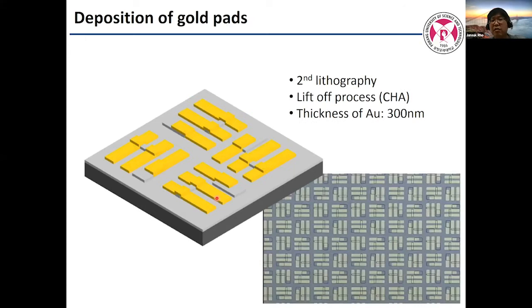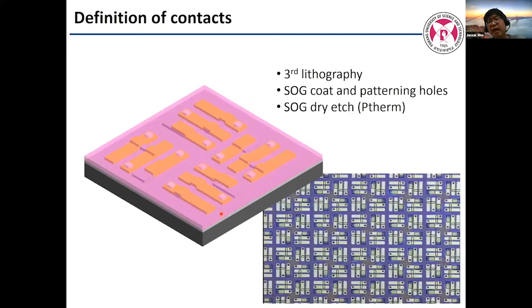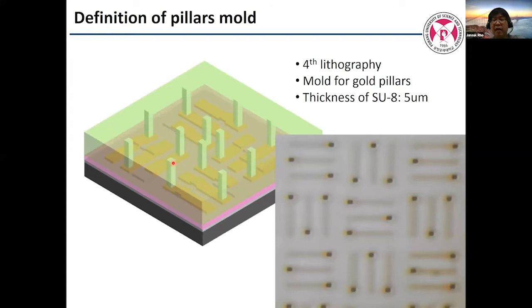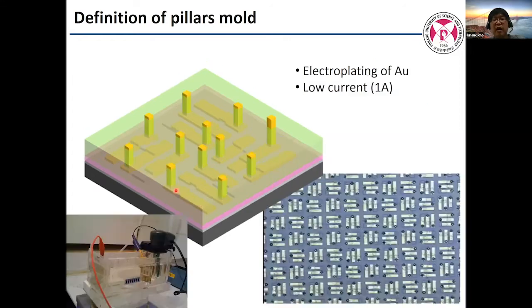And then this is the second lithography. You can see the alignment, as usual, the micro mask aligner can do alignment very well. This is a gold pad lithography, and then gold deposition and lift off. Third, we coat with spin-on glass, which makes the electrode safer during the electroplating. Anyway, you can see here the anchor. The anchor is the starting point of this long pillar. So this is the fourth lithography in SU-8. We make this long via hole, and electroplating is done here.